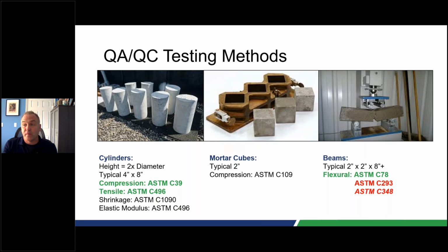And then when you measure flexural strength, typically these are measured on 2-inch by 2-inch by 8-inch beams for mortars. And we can help people with that. There are multiple tests for measuring flexural strength. They are not all the same. The one in the picture shown is ASTM C78. This is what I would refer to as a 4-point bend. ASTM would refer to it as a third-point loading, which means in this case, you've got 2 points on the bottom and 2 points on the top. Those 2 points on the top distribute the load in thirds. That's why they call it third-point loading.